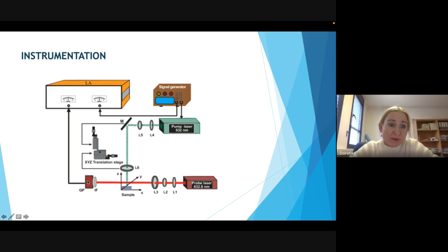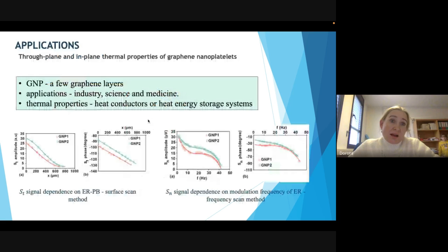Then detection is performed by quadrant photodiodes equipped with an interference filter that lets through only the probe beam to reach the detector, and the signal is collected by the use of a lock-in amplifier. The lock-in amplifier has the advantage that it measures the signal of a chosen frequency, so it measures only the signal that has the same frequency as the modulation frequency of the excitation radiation. Due to that, you are able to measure a low signal in the presence of high noise. Yeah, so this is the big advantage of the technique.